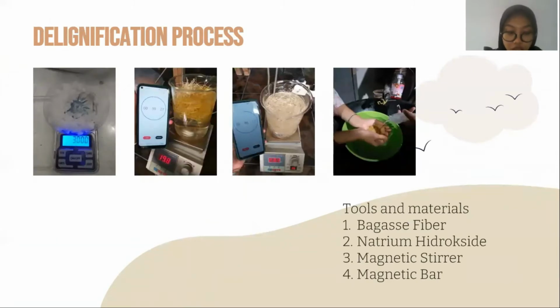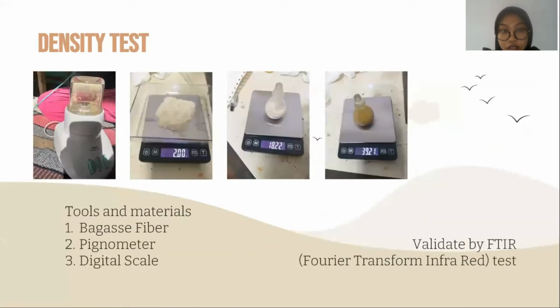The first stage in this research is the delignification process. This process uses 0% and 3% natrium hydroxide for 1 hour. In this process, a magnetic stirrer is used to assist the immersion process. After 1 hour, the fiber is washed and then dried and prepared for the next process. The next is density test. The early stage of this process is weighing the pycnometer and fiber. After that, the calculation uses the basic formula mentioned in the basic theory.